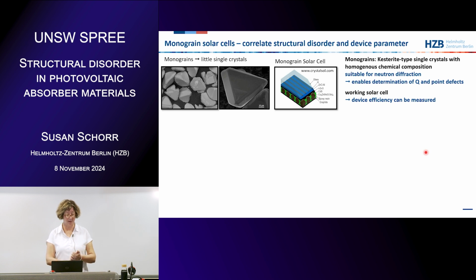One slide about the monograins, because monograins are little single crystals, and in principle the single crystal inside is homogeneous, and also in a batch it's very homogeneous. It could be also sometimes inhomogeneous when something went wrong in the growth process. They are grown in potassium flux, but they show a good homogeneity.